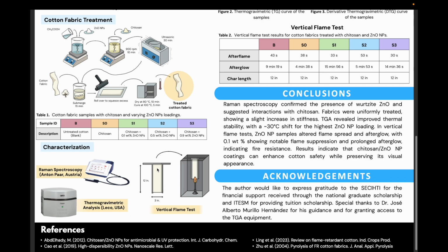And for characterizations, Raman spectroscopy was used to confirm the presence of wurtzite zinc oxide and to detect possible interactions with chitosan. The thermogravimetric analysis was performed to evaluate the thermal stability of the samples. And finally, a vertical flame test was conducted to study the flame resistance and afterglow behavior.